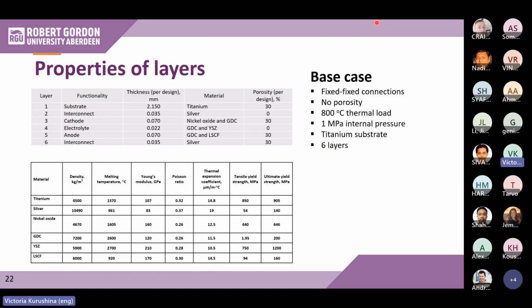So the tubular cell here is being fabricated in the lab and can be presented for thermomechanical analysis as 6 layers of the structure, including the substrate as the inner layer, silver interconnect, cathode, thin dense electrolyte, and the anode layer. And also on the top we would have a silver interconnect layer. So this is a simplified cell we're going to test for the thermomechanical part. And the total thickness of the undeformed cell is about 2.5 millimeters. And the materials used here include titanium, silver, nickel oxide, GDC, YSZ, and LSCF.